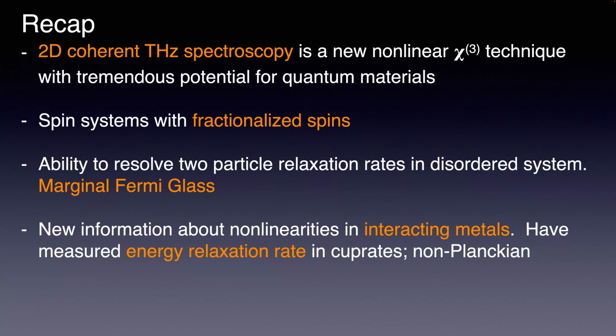One is that it is an increasing function of temperature in the range that we've measured, right? So you could imagine a world, I don't think that's the world we live in, where really soft phonons were giving linear in T resistivity with an almost Planckian coefficient, but they would result in an energy relaxation rate which was a decreasing function of temperature. So that's an old prediction that goes back to Allen, and I'm sorry I had to rush through this here. In contrast, what we see is linear in T momentum relaxation, and also an increasing function of temperature in the energy relaxation rate. So one of the things our study does, I think it does some other things, is completely rule out phonons as the source of linear in T resistivity in the cuprates.